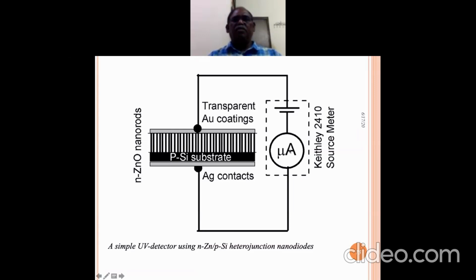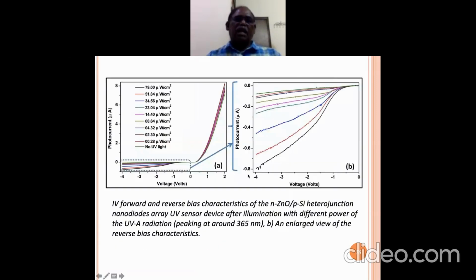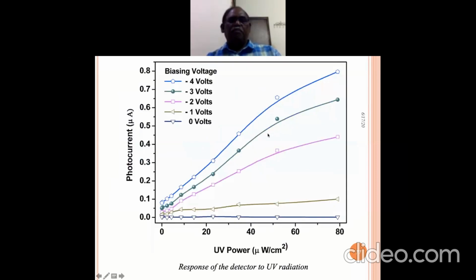We had studies in reverse bias mode, and you can see that with applying more biasing you get more and more photocurrent. But at the same time, if you have fixed biasing and you change the UV power, you see that the photocurrent increases. And the properties of this device we found better than the commercially available ones. We tested with a couple of other commercially available sensors of this kind for monitoring.